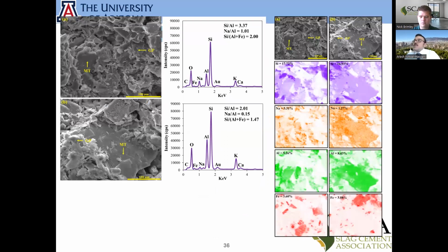This graph shows the microstructure level, before the wet and dry cycles and after 14 wet and dry cycles. You see that at the microstructure level, the only thing that is changing majorly is that some of the sodium hydroxide that did not participate in the geopolymerization is washing away. This is mainly the reason that the strength of the samples is decreasing.